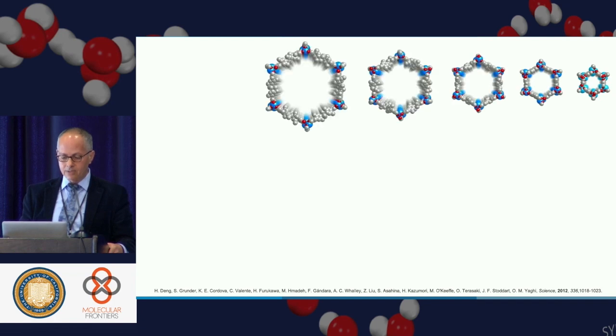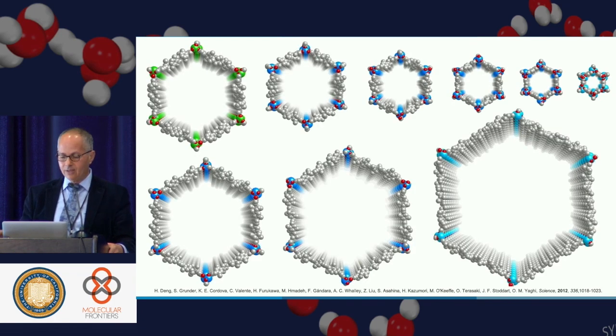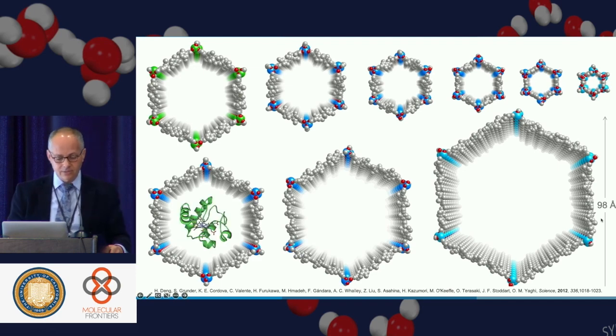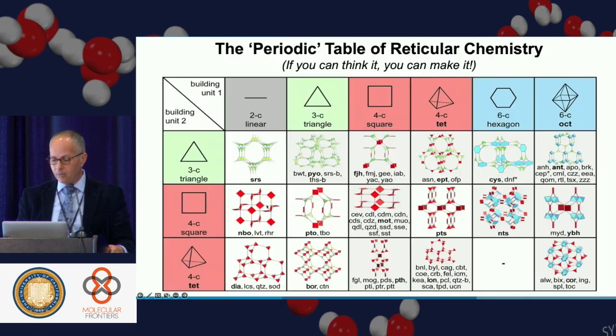And just for a dramatic effect, you could progressively expand the pores so that now you can go from pores that are only 0.1 nanometer to pores that are 10 nanometers. And you can do this incrementally. And if you like, you can also study the inclusion of proteins and enzymes inside the pores. So what I'm trying to say is that if you think it, you can make it, because the chemistry works.